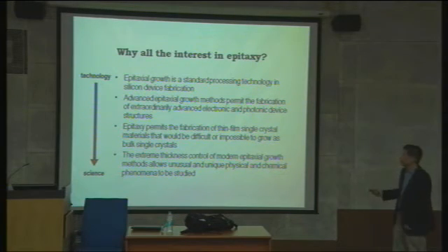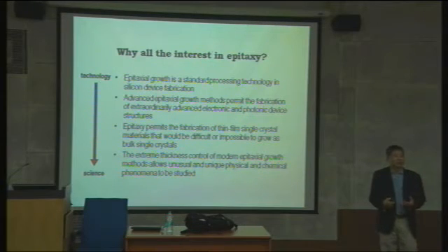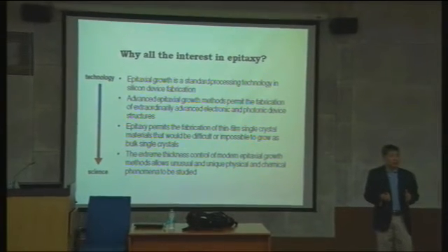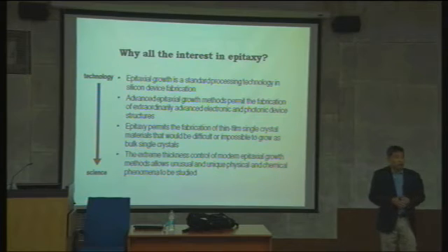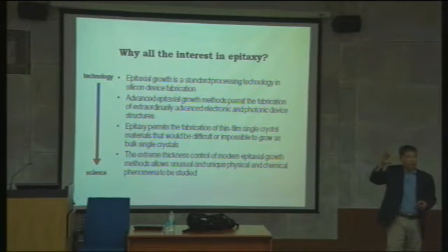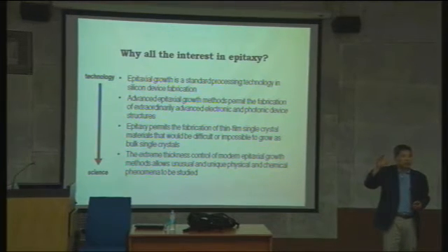So you have two extremes, but in between, there are thin film single crystal materials that would be difficult, possibly impossible, to grow as bulk single crystals. Sometimes a bulk single crystal cannot be grown because the phase diagram doesn't allow it, or segregation doesn't allow it, and that phase does not exist at all. But thin films allow you to grow metastable phases that bulk single crystals never form. Heteroepitaxy allows you to grow certain phases and structures that have never been grown as single crystals. Why? For example, the bulk structural phase is the pyrochlore phase.